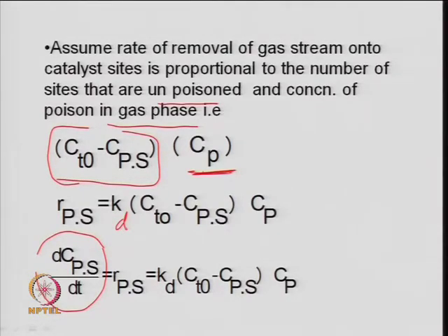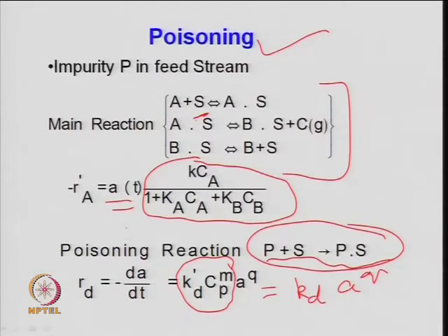This is based on the surface reaction which we are assuming in terms of the mechanism here for the poisoning, and one can directly correlate it in this form also by just doing the experiment, calculating the rate with time on stream, and then calculating the order of deactivation and the decay rate constant.